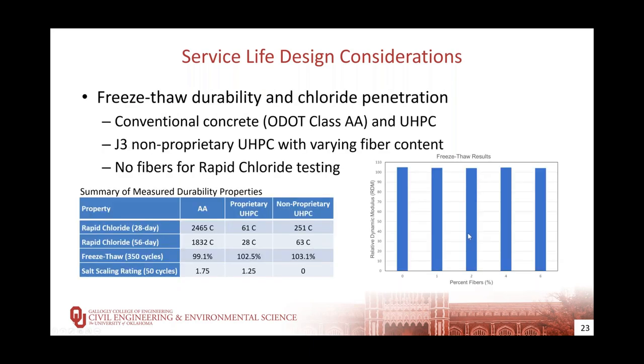We examined freeze-thaw durability and chloride penetration first for a conventional Oklahoma DOT Class AA bridge deck concrete, a typically proprietary UHPC, and the J3 non-proprietary UHPC mix. We then looked just at freeze-thaw durability for the non-proprietary UHPC with varying steel fiber content. For the rapid chloride ion permeability test, we only examined the matrix since the test uses an electrical current and the fibers would short circuit the test.